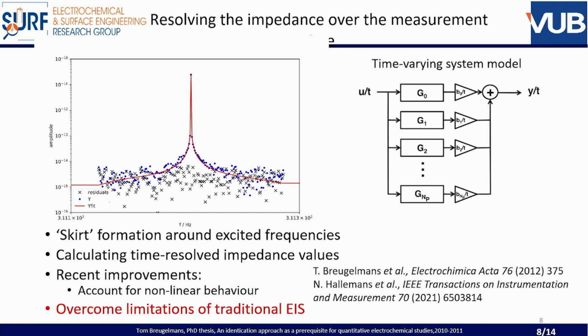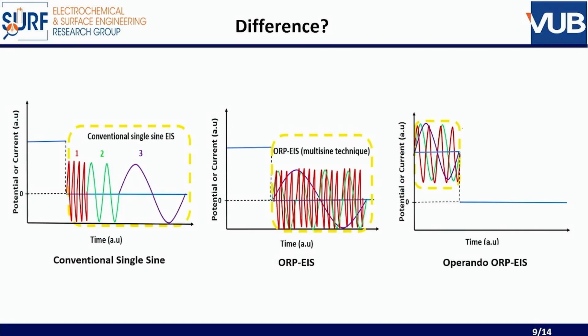We can also define what we call the operando impedance, and this is very interesting for looking at systems like batteries and so on, because you measure what is called the instantaneous impedance. So here, to summarize a little bit, this is the conventional single sine impedance. You usually go from high frequencies to low frequencies, so there is a time domain. If your system is changing in that time domain, you have a problem, because what you measure here is not representative anymore. Especially with corrosion, this is the case.